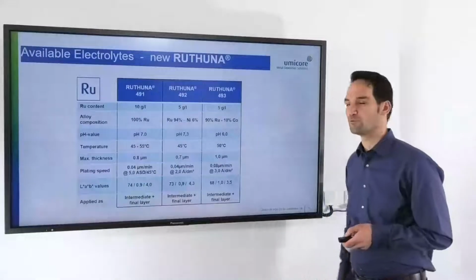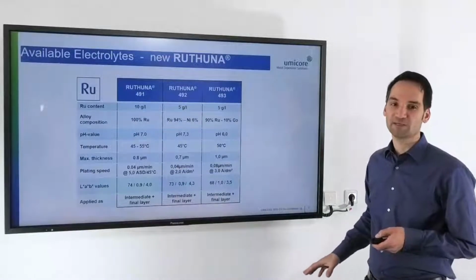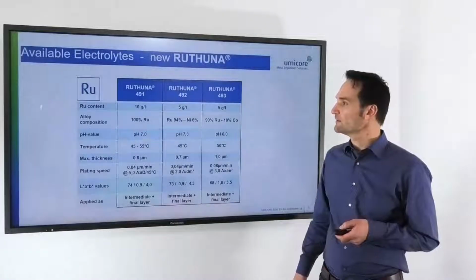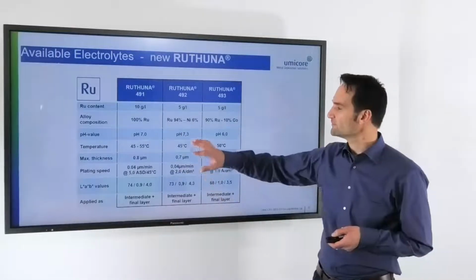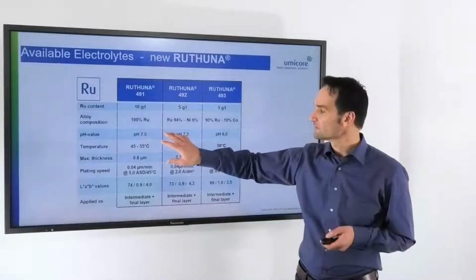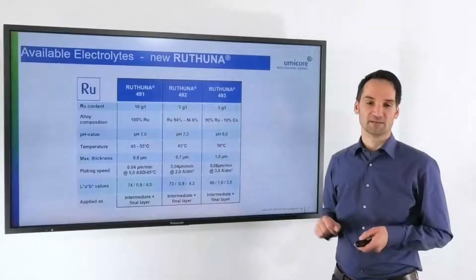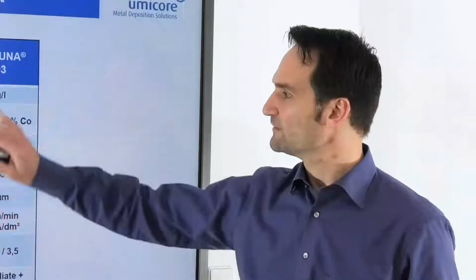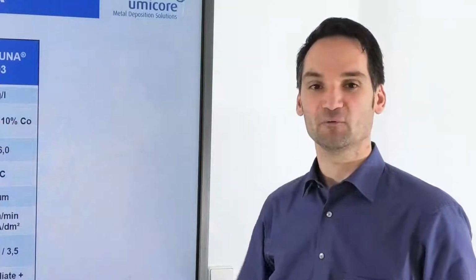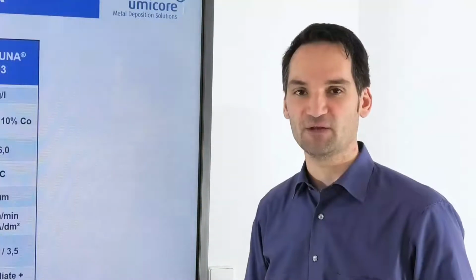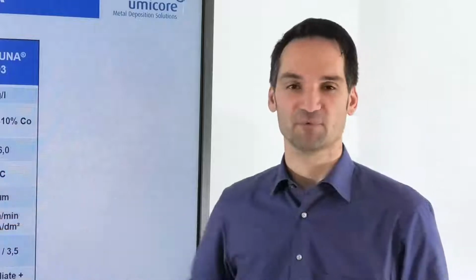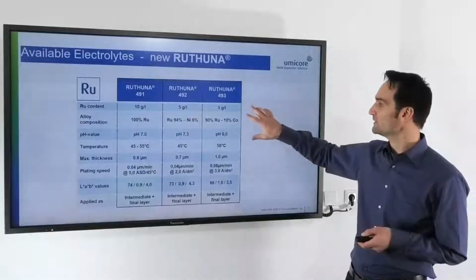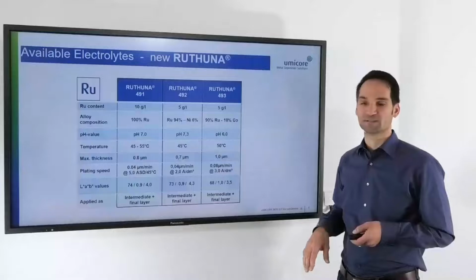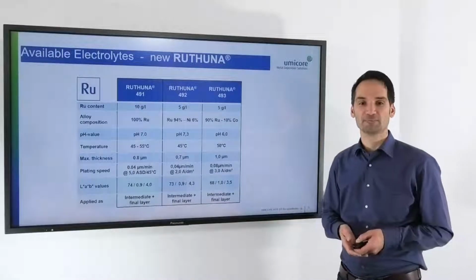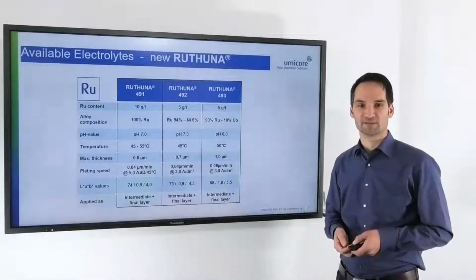So what is the new RUTHUNA? We have developed three new kinds of electrolytes. The RUTHUNA 491 is a pure ruthenium based pH 7 plating. If you have a look at the 492, this is an alloy with 6% of nickel and can be used as a replacement of palladium nickel applications and comes with a pH of 7.3. And additionally, the 493 is a 10% alloy to the ruthenium, which gives you an additional saving effect.